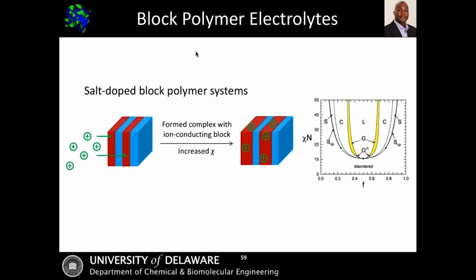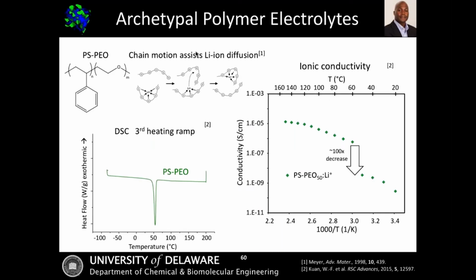Typically how that works is I take a block copolymer and find some way to add that salt, either through co-dissolution, and that salt is going to do several different things. It can change the morphology. It can segregate into one domain versus the other. It can lead to transient behavior in terms of glass transition temperatures, and it can also influence the processability of the materials. So what's the archetypal system and where did this all start?